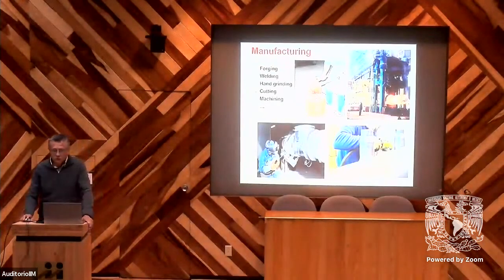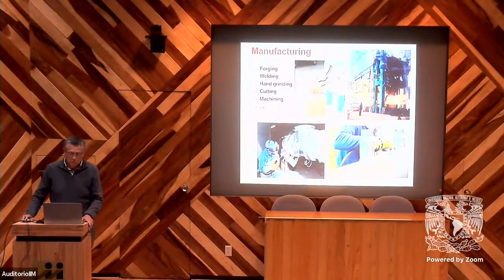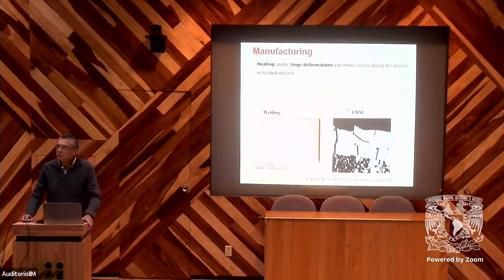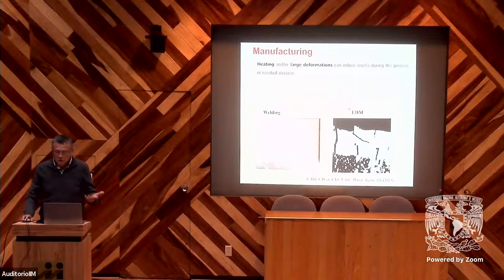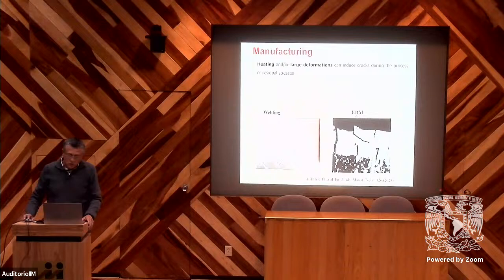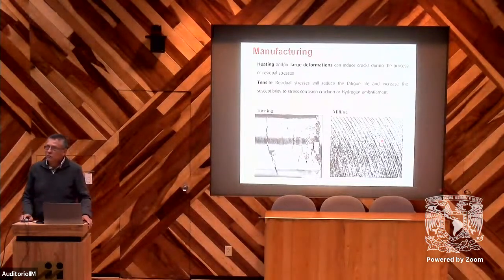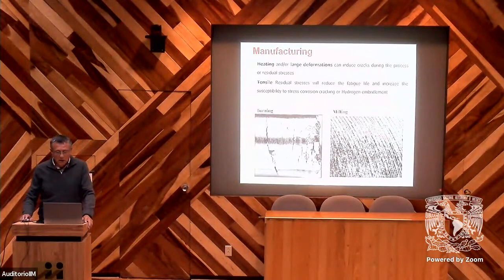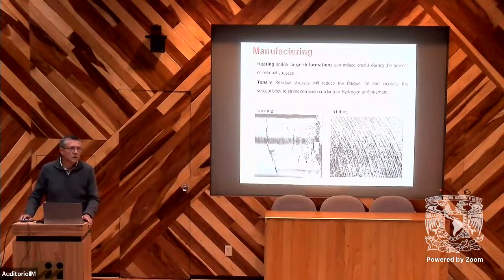So we know that manufacturing processes such as forging, welding, grinding, cutting, and machining use high levels of deformation and heating, and this will sometimes lead to cracking or to residual stresses. We know, for example, in the case of welding or electric discharge machining, we can have some cracks during the process, or we can have residual stresses. Tensile residual stress will reduce the fatigue life of a component, and also increases the sensitivity to stress corrosion cracking or hydrogen embrittlement.